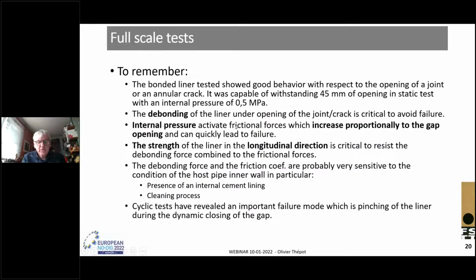So, what can we remember? First, the bonded liner tested was capable of withstanding 45 millimeters of opening in static tests with internal pressure of 0.5 megapascal. Remembering that 12 millimeters was a representative value, it is, I think, a good performance. The debonding of the liner and the opening of the joint is critical to avoid failure. Internal pressure activates frictional forces, which increase proportionally to the gap opening and can quickly lead to failure.